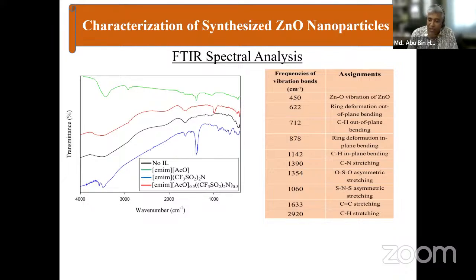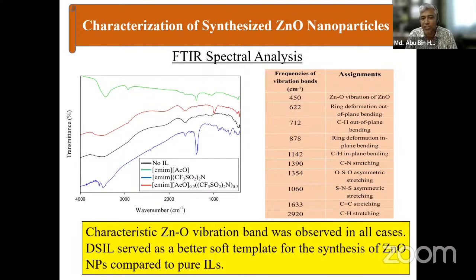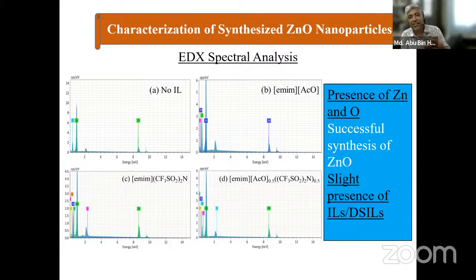When we compared the Fourier transform infrared spectral analysis, we found all the profiles necessary to establish zinc oxide nanoparticles. The characteristic zinc oxide vibration band was observed in all cases. Double salt ionic liquid served as a better soft template for the synthesis of zinc oxide nanoparticles compared to pure ionic liquids. When we checked the EDX, energy dispersive X-ray spectral analysis, we could confirm the presence of zinc and oxygen, which confirmed the successful synthesis of zinc oxide nanoparticles. But the problem is we could also find the presence of slight amounts of ionic liquids or double salt ionic liquids with the zinc oxide nanoparticles. Some are adhered to the surface of the zinc oxide nanoparticles.